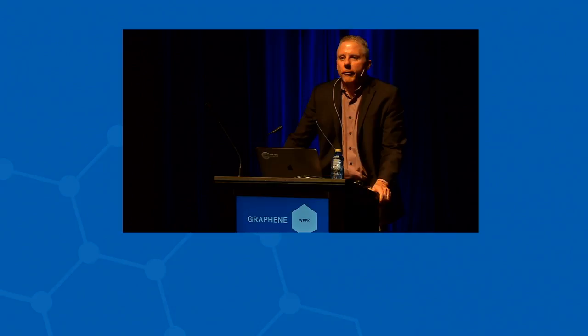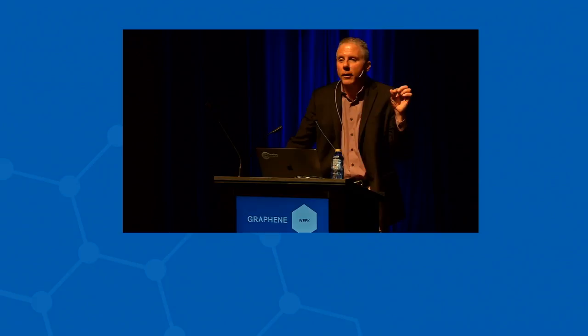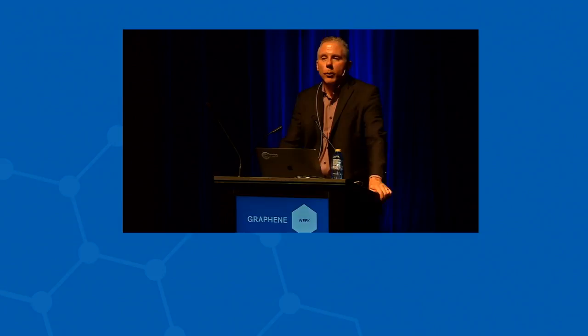Yes, okay, so black phosphorus, you highlighted one of the challenges of working with black phosphorus. And indeed, of course all of the synthesis is done in a glove box environment. And we monitor carefully, by studying the composition and looking at the properties of the material with Raman spectroscopy, what happens over time. And we can see, of course, examples of oxidation. And in fact, wherever there is oxidation, the quantum well properties change. Effectively, they get thinner. So the optical intersubband absorption acts as a very sensitive indicator of the effective remaining black phosphorus thickness. But encapsulation is certainly an important issue for black phosphorus.